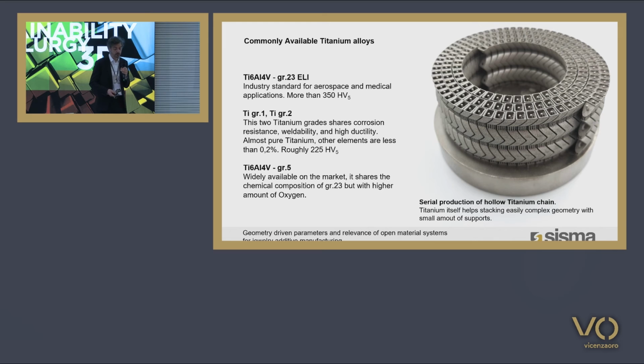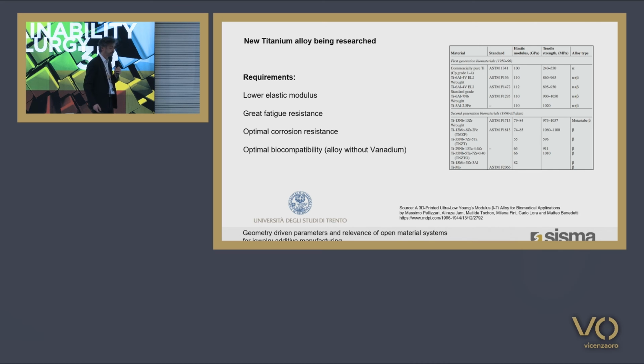And then we have titanium 6.4 grade 5, already widely used in the watchmaking industry, and it might be considered a benchmark there. But for most of these applications, grade 23 might be the best choice. It's basically similar in terms of chemical composition, but it's more pure in terms of oxygen and contaminant quantity.